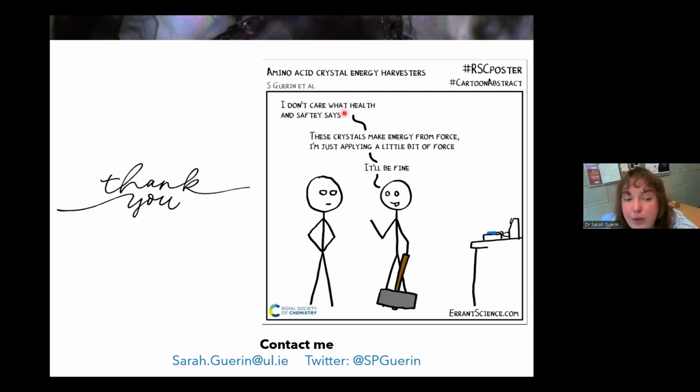That's a great question. Yeah, we haven't worked too much with lower dimensionalities of materials. We have done one collaborative study where we did see that reducing the dimensions in that case increased the piezoelectric response, but I don't think we've done enough systematic studies to definitively say if there's a direct effect. But the problem in 3 dimensions is the more complicated your structure, generally the more dipoles that are going to be in your unit cell, and the more cancellation you get of that response. So even if you have a molecule with a very large dipole, that's not enough to predict its piezoelectricity. You need to see how those molecules pack together in 3 dimensions.